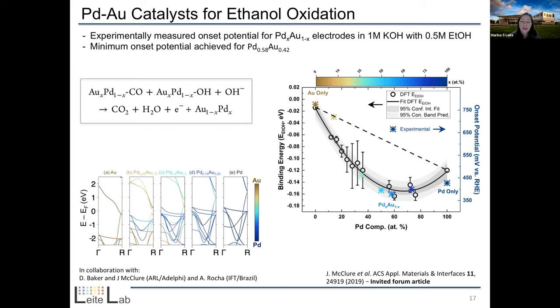So essentially palladium gold as an alloy, this was known before, is a good catalyst, but then here we could find what is the ideal chemical composition that can actually bring it to a minimum onset potential. And again, we explained all that was going on in terms of the band structure of these metallic mixtures as well.